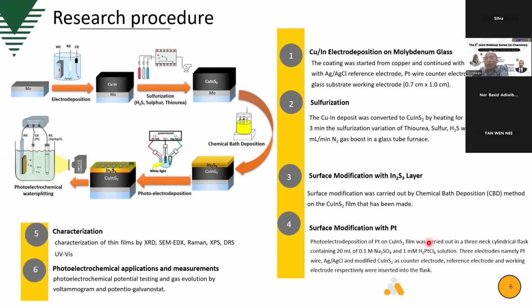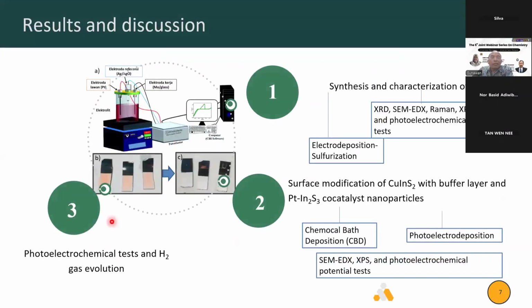And then surface modification with platinum. In this case, we use a 1 millimolar H2PtCl6 solution, with illumination for deposition of platinum at a potential around 0.1. Then we can continue to the results and discussion.